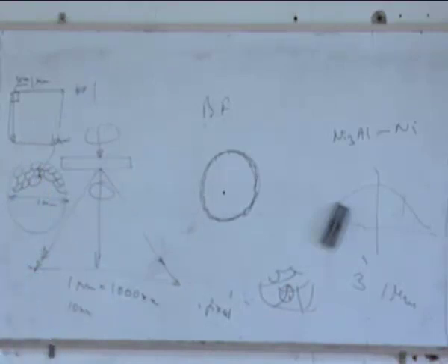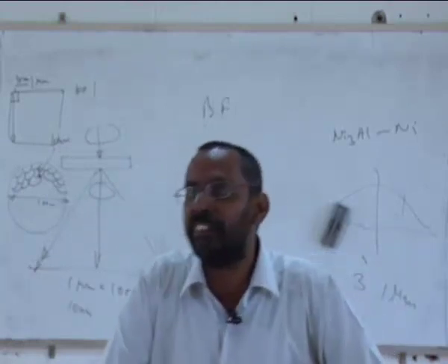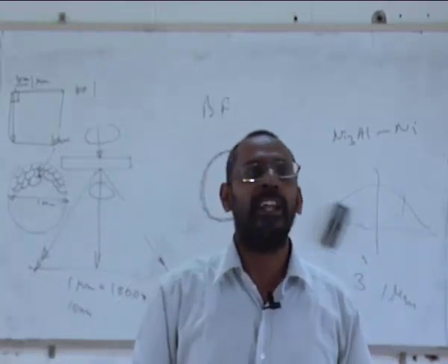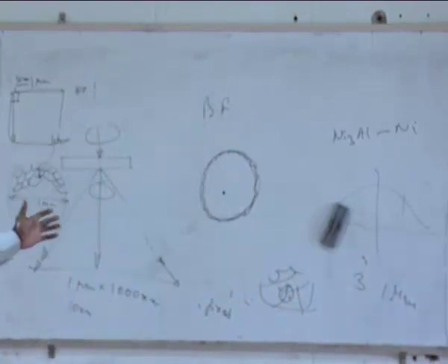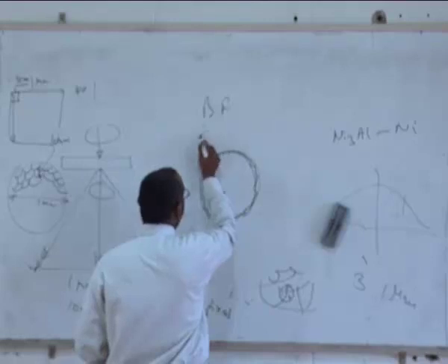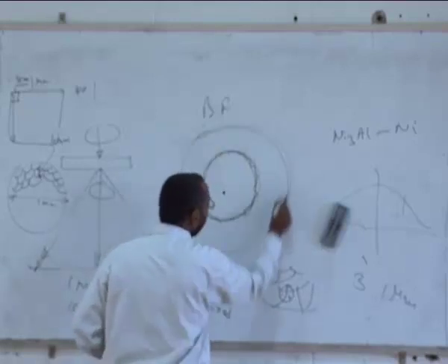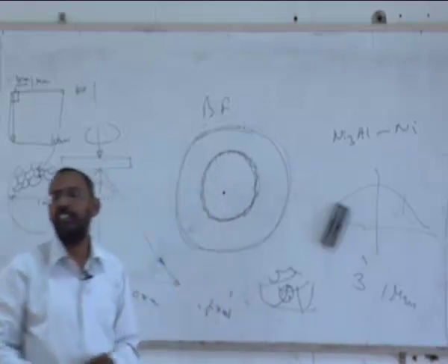And because there is no periodicity, the scattering is not a clear Bragg's kind of scattering, it's a random scattering, and that is why you get that ring. So this is what you see, and you get a diffused ring, and sometimes you get another second diffused ring also. Again, in the same way, I can talk about first nearest neighbor and second nearest neighbors.